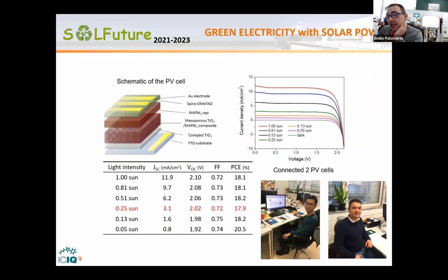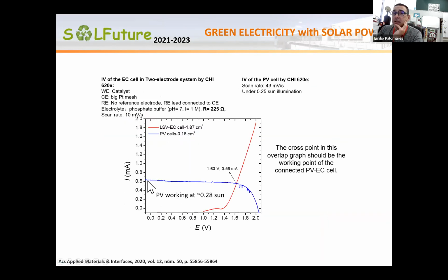Why was this a challenge for us, using these perovskite solar cells? What was our goal? Our goal was not to compete with people on efficiency. Our goal was to use those solar cells to power catalysts that can either do water oxidation or, as in the last example I will show today, CO2 reduction. So basically, we combine two of these solar cells, and for example, a quarter of the sun, so 0.25 suns, we got efficiencies of about 17-18%, and we have enough current and voltage to drive this water oxidation with a ruthenium catalyst. This is the IV curve of the tandem cell.